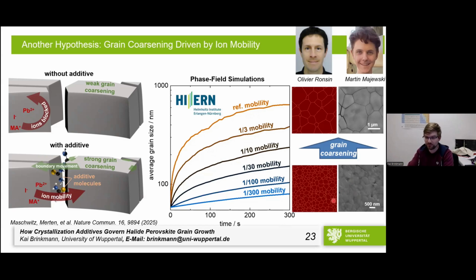That we end up with the stuff that we get without the additive. And if we have something with the additive, we actually end up with these large grains that look surprisingly like the grain size distribution that we get with thiourea. And for this, the mobility needs to be much higher.